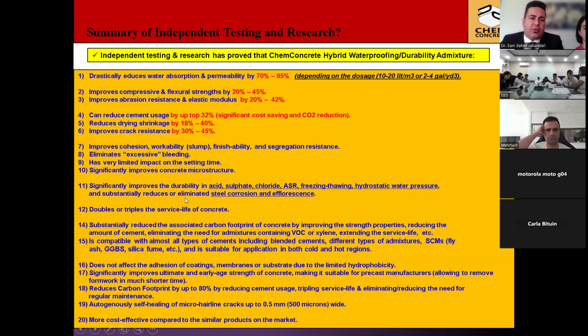It substantially reduces or eliminates steel corrosion and efflorescence, and doubles or triples the service life of concrete. It substantially reduces the associated carbon footprint of concrete by improving the strength properties, reducing the amount of cement, eliminating the need for admixtures containing those nasty xylene, extending the service life, etc.